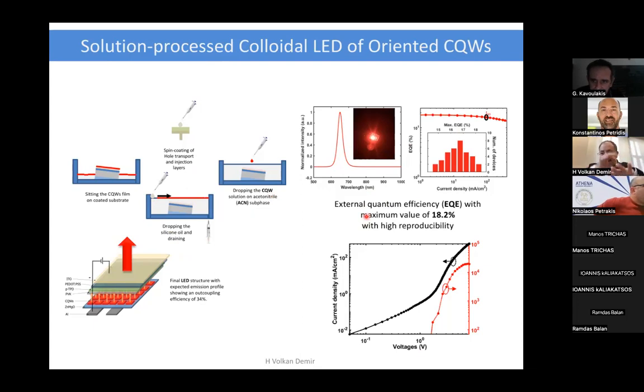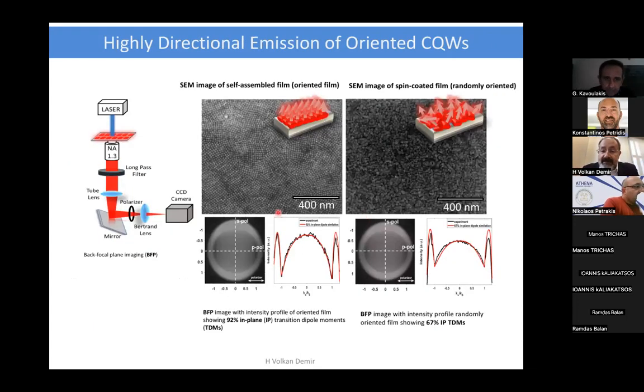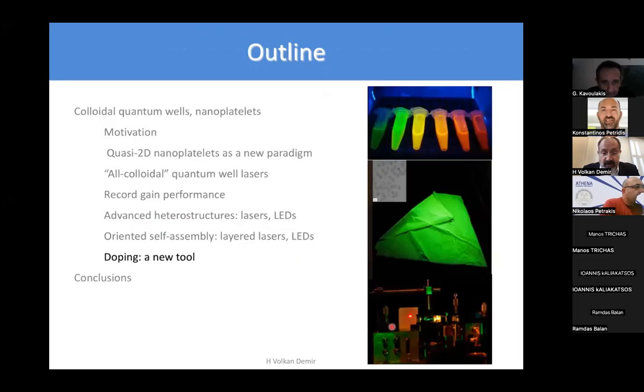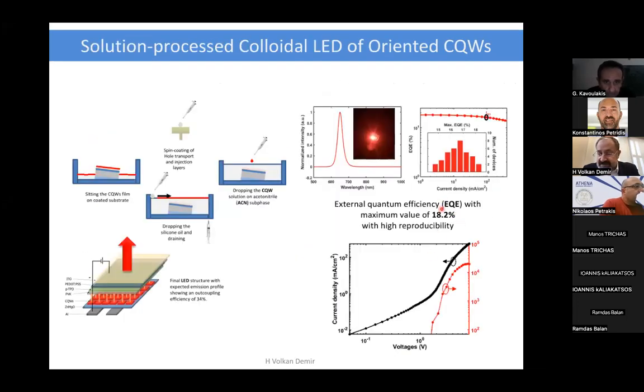Where we have spin-coated, indeed the dipole moments are all over the place, randomly oriented, and this indeed limits the outcoupling. So this is a comparative study, again, a self-assembled, face-down oriented nanoplatelet film. And this is the spin-coated version, everything identical except for the assembly. And in this case, as one would expect, we can achieve, this is an experimental result, 92% in-plane transition dipole moments, as opposed to the typical randomly oriented case, where we experimentally observed 67% in-plane transition dipole moments. This, as a result, increased our efficiency to 18.2% using an all-solution approach.